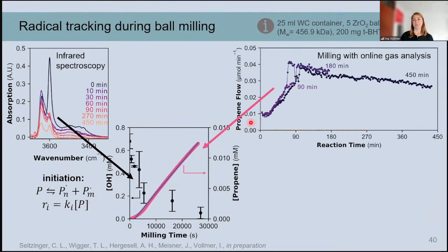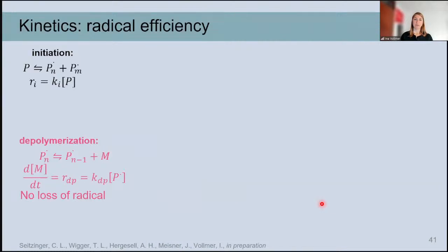At the same time, we can also look at the rate of monomer formation from just the flow of propene coming out of the reactor. This is shown here in the pink line. So this is the depolymerization rate. And here we then try to compare the depolymerization to the termination.